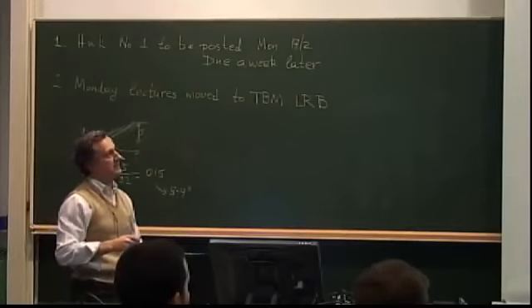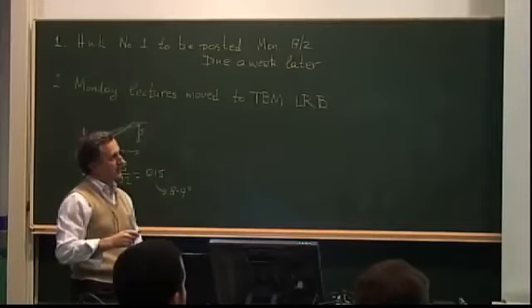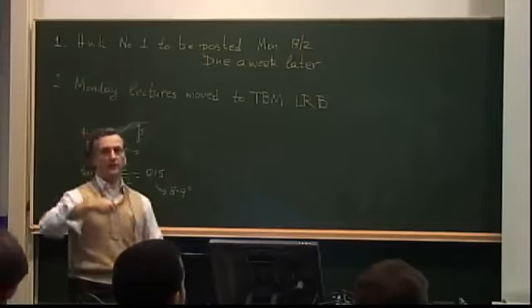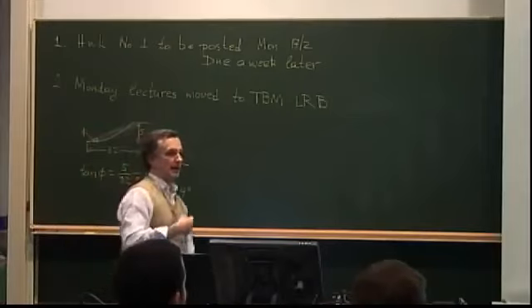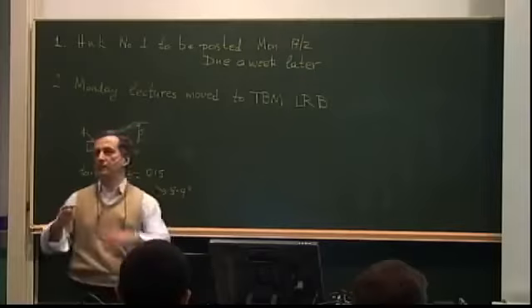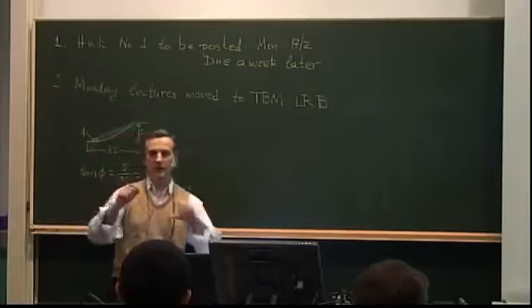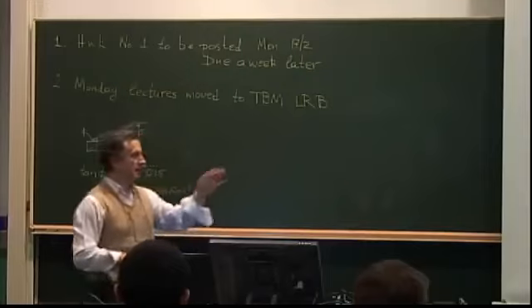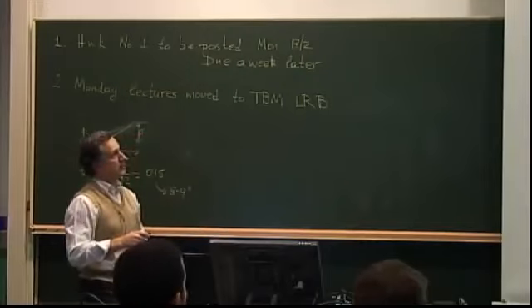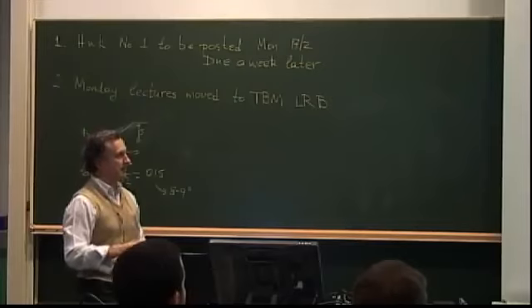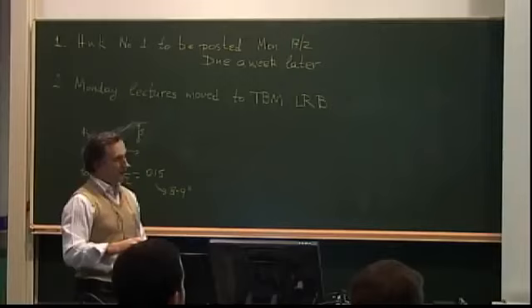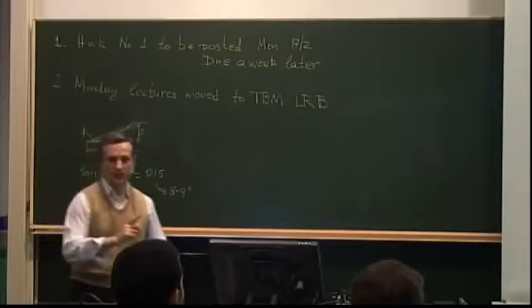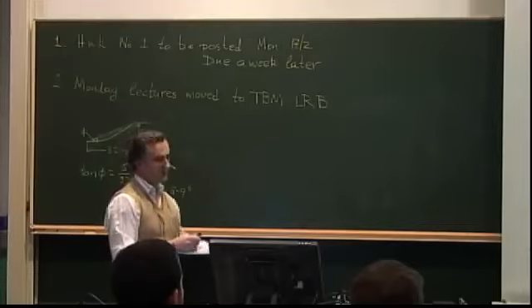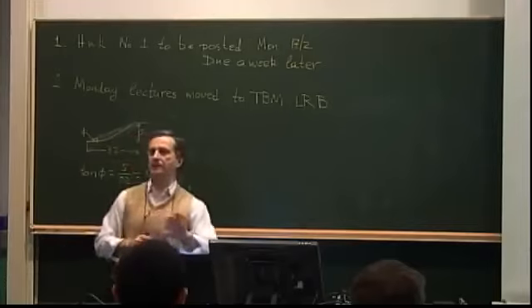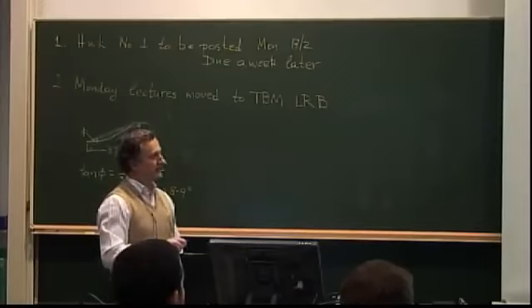What happens is, if you think about the individual constituents, fiber and matrix, then the failure modes are quite different than tension and quite different than a pure strength kind of failure. In a metal, if you do compression, locally there is some shear and the metal yields, that's it. In a composite, you can have what's called fiber kinking. Fiber kinking is shown here. Nominally, the fibers are straight, but locally, they won't be perfectly straight. And even if they were, under compression load, they actually start bending out of shape. It's like a local buckling-driven phenomenon over a very short wavelength. And in the end, they develop this kink.